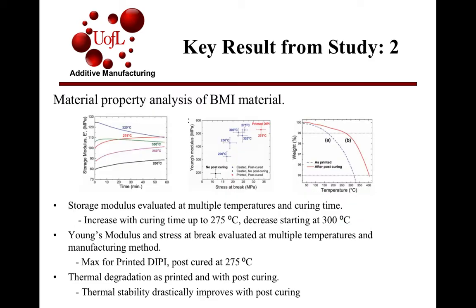The second result of the study was to look at the material property analysis of the BMI material. First, with the graph on the far left there in the middle, the researchers looked at the storage modulus, and they evaluated storage modulus at multiple temperatures and curing times. It can be seen on this graph that the storage modulus increased with the curing time up to 275 degrees, and then at 300 degrees Celsius and above, the storage modulus started to decrease with curing time.